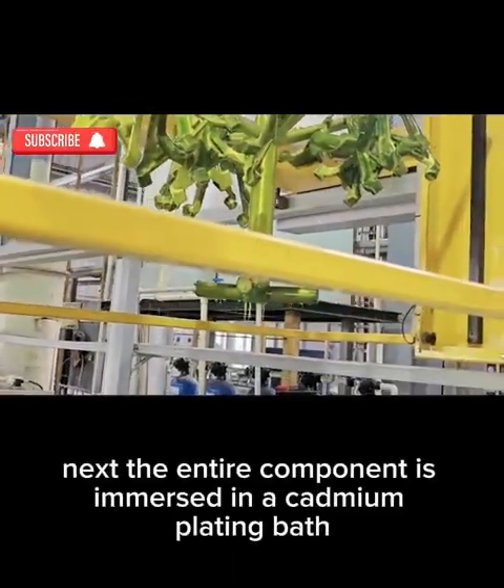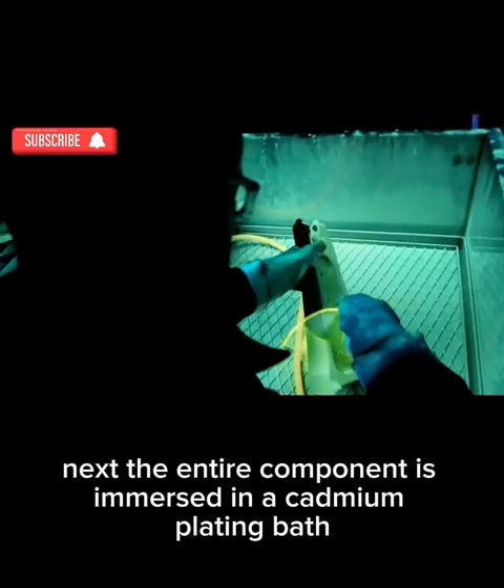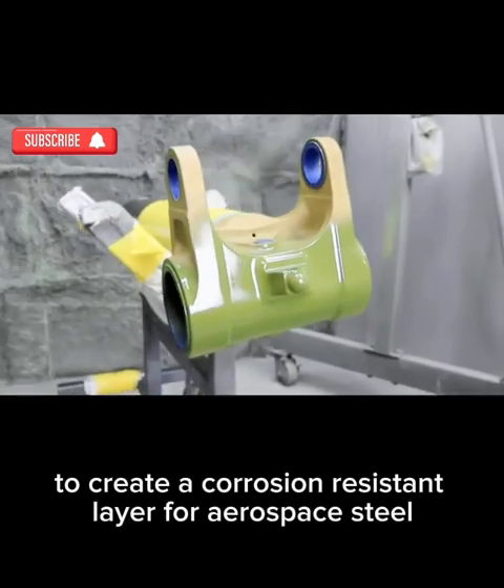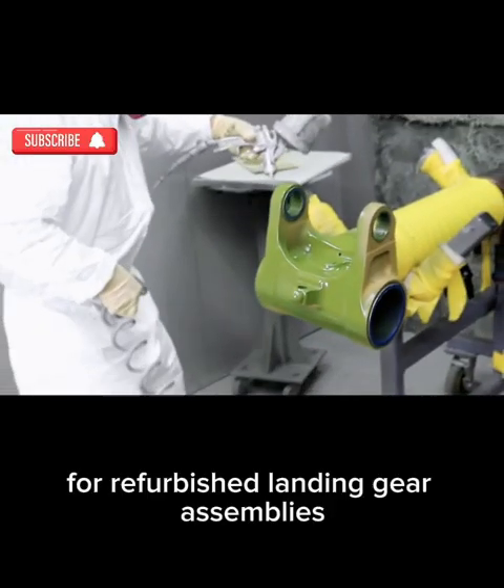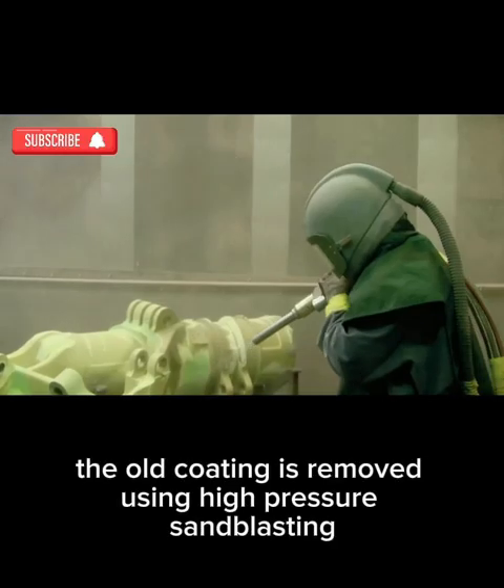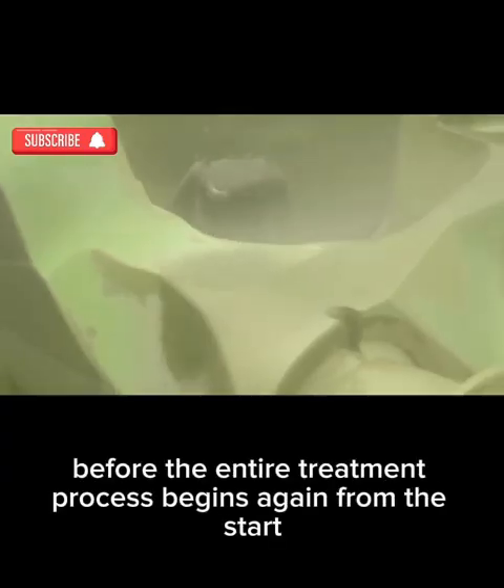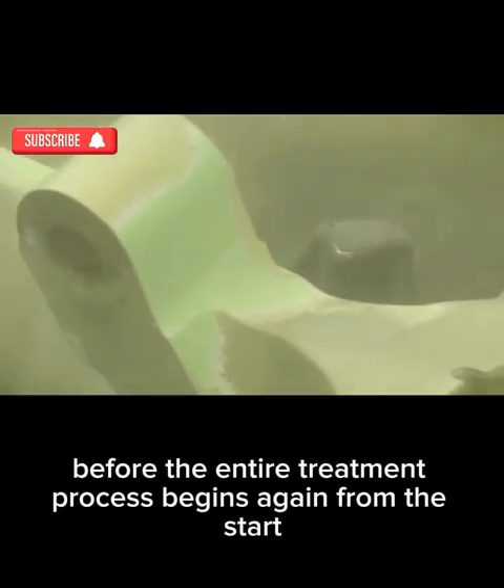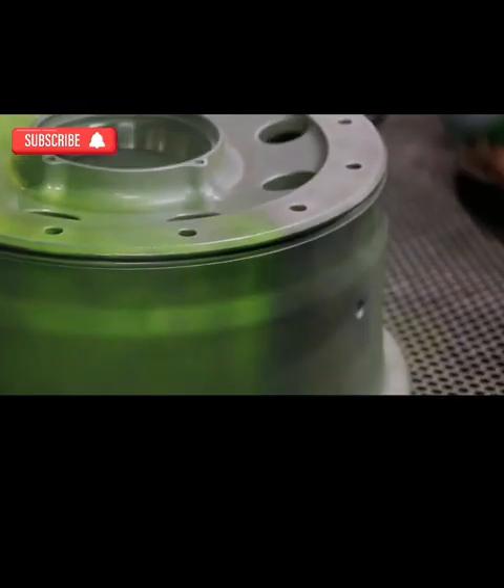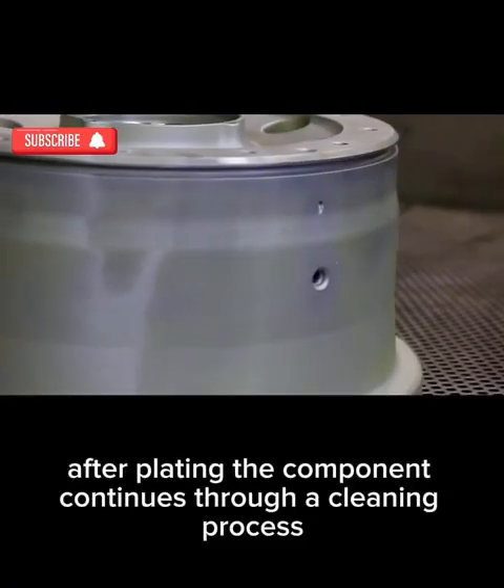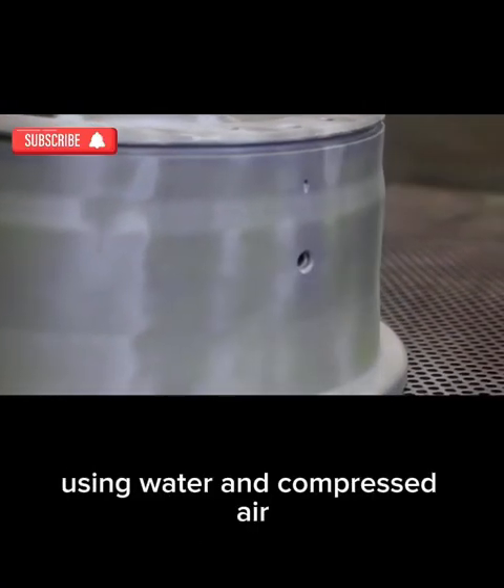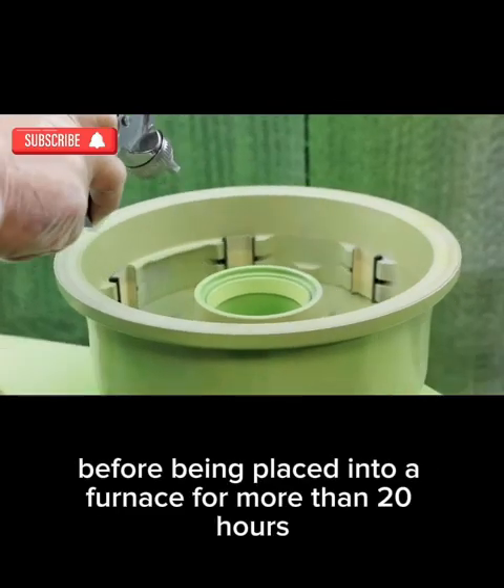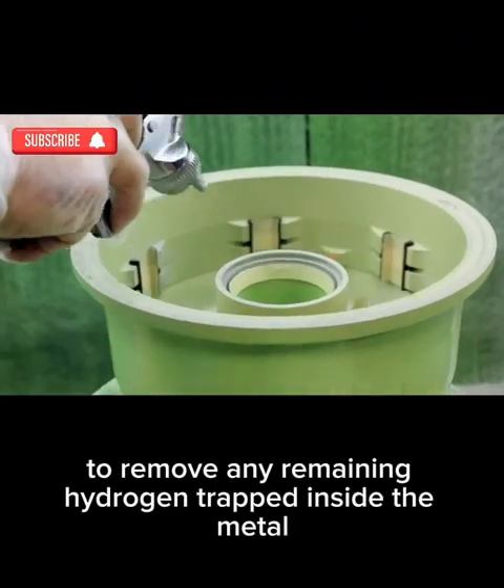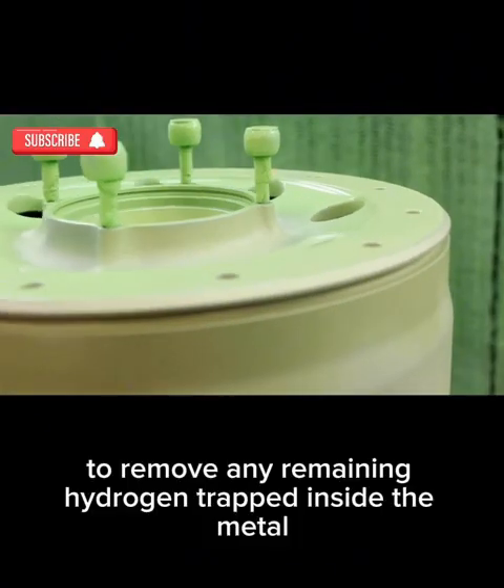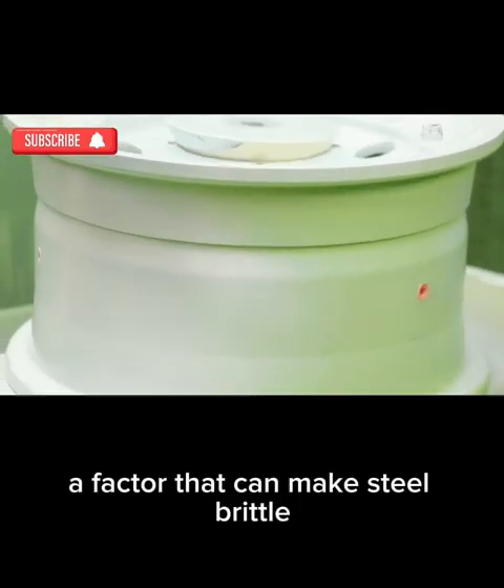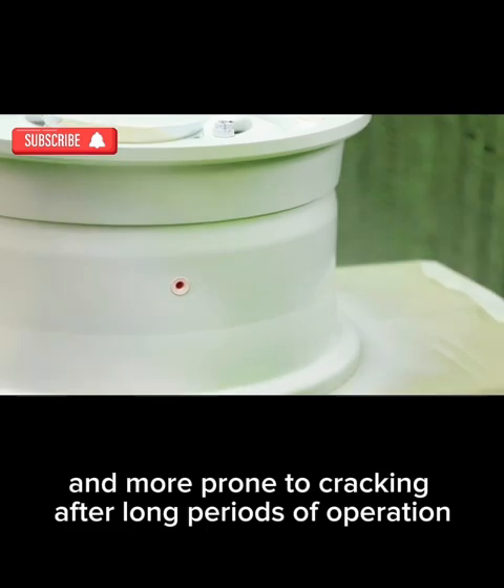Next, the entire component is immersed in a cadmium plating bath to create a corrosion-resistant layer for aerospace steel. For refurbished landing gear assemblies, the old coating is removed using high-pressure sandblasting before the entire treatment process begins again from the start. After plating, the component continues through a cleaning process using water and compressed air before being placed into a furnace for more than 20 hours to remove any remaining hydrogen trapped inside the metal, a factor that can make steel brittle and more prone to cracking after long periods of operation.